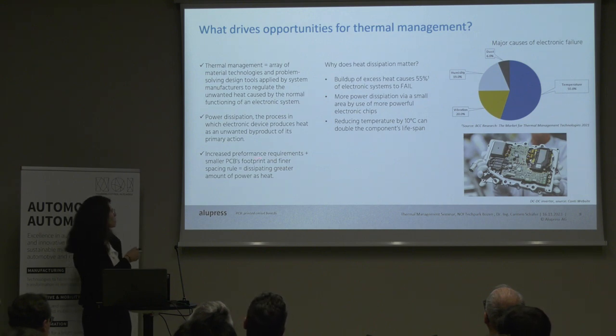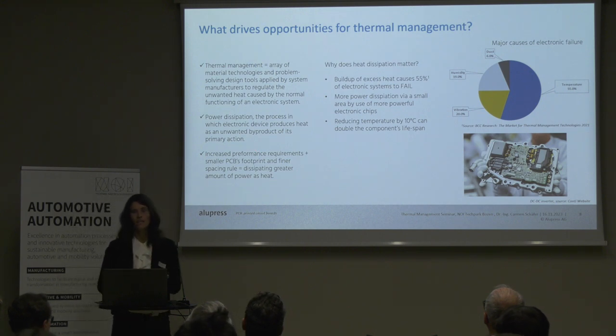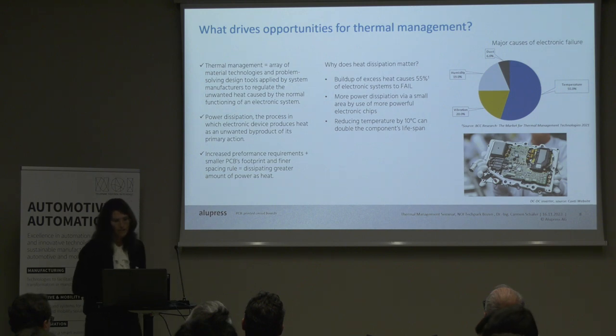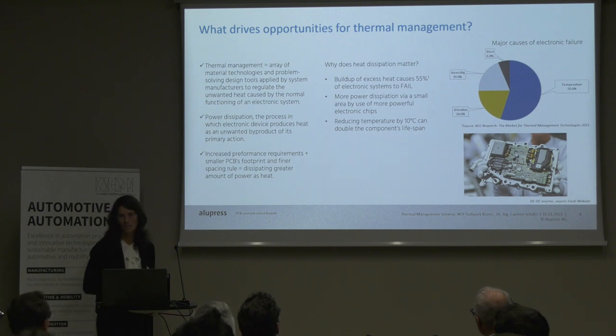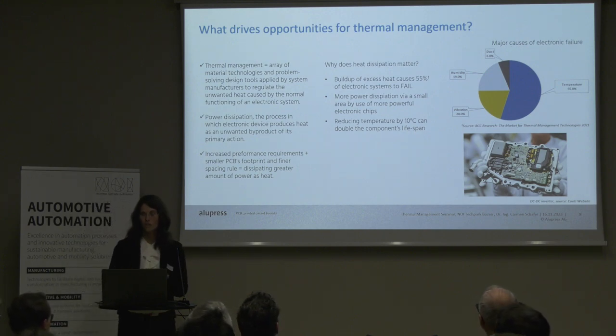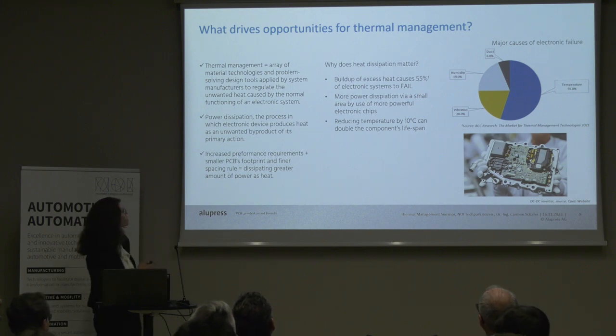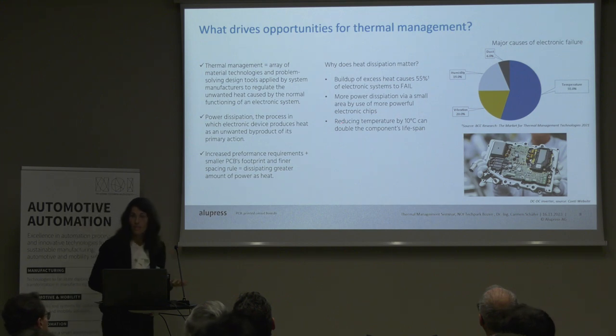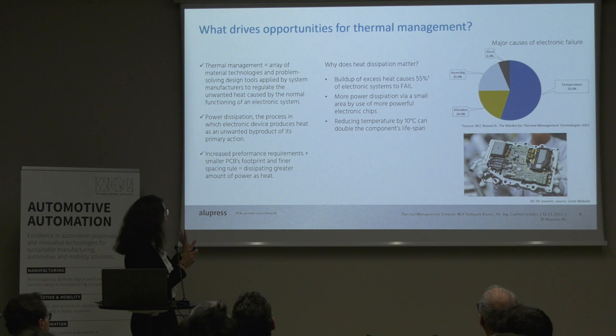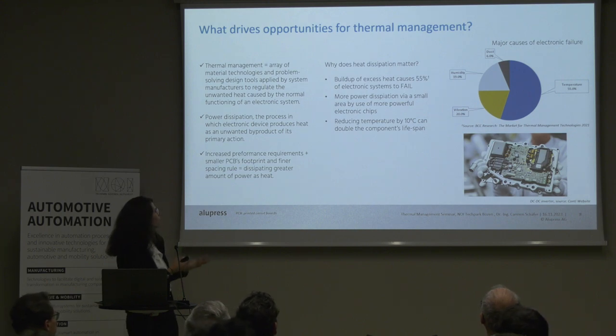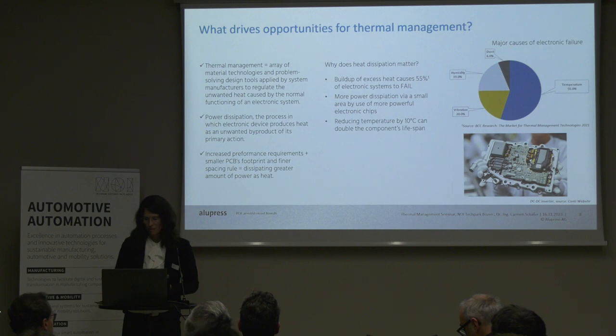And on top, we have increased performance requirements, smaller PCB footprint, smaller spacing, and that means, again, more heat per area. If you look at this graph, you see that in 55% of the cases, these electronic components fail just because of temperature. And this will get just worse with the SiC chips, and that means we need to remove it. If we reduce the temperature by 10 degrees, for instance, we can double the lifetime of this component, more or less. And of course, we need better efficiency for the more powerful chips per area.